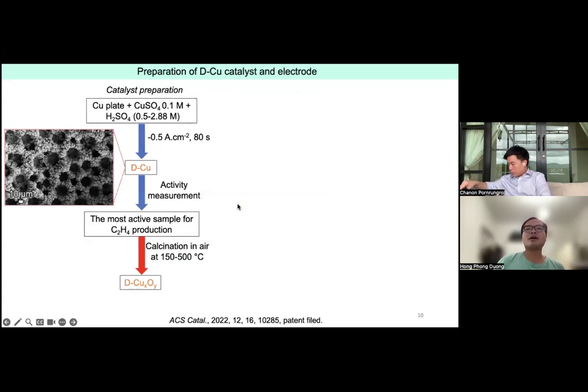So how did we make this catalyst? It is very simple. We perform a method called electrochemical reduction. Basically, we just put a copper plate into a solution of copper sulfate with different acid concentrations. When we apply the current density, the copper sulfate is reduced into metallic copper. At the same time, we have the hydrogen evolution reaction, which makes a lot of hydrogen bubbles on the surface of the copper plate. So we can control the porosity and the dendritic growth of this catalyst. And then we can just scratch the electrode to obtain the copper powder.